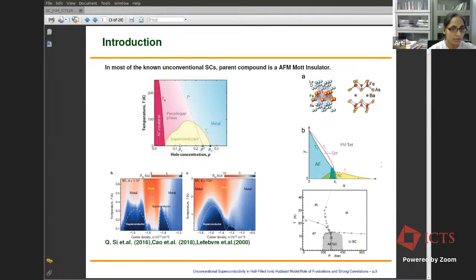So if you look at the phase diagram for all these materials, you will find that there are some very common features. For example, the parent compound in all these materials is a strongly correlated antiferromagnetic Mott insulator. Pnictides are a bit of an exception because the parent compound is not a Mott insulator, but they have antiferromagnetic spin density wave order, and the system still has moderate enough correlations.